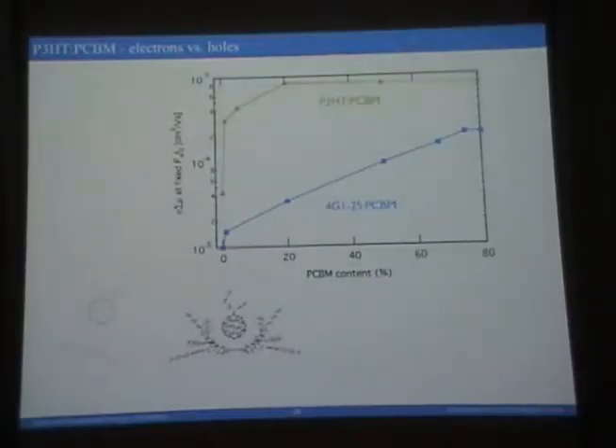signal. I should add, it's only 6 months ago that I learned this. Maybe it was 10 months ago. Here is what happens if you put differing amounts of PCBM into a dendrimer. Don't worry about the name. And the same data for PCBM, P3HT. And this is the signal at t equals zero. So what this shows us, as we add PCBM with P3HT in the system, the signal jumps up and then plateaus off. And that's because the signal goes up because we're detecting the electrons. And in the PCBM dendrimer case, it doesn't, so the signal just creeps up. And this is basically the yield of carriers going up as you add PCBM. It doesn't work as a device.